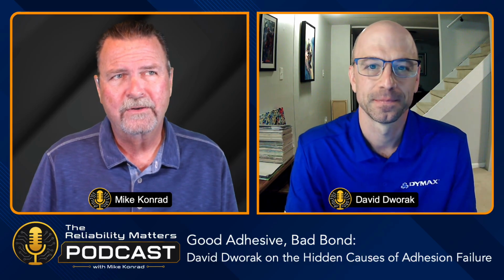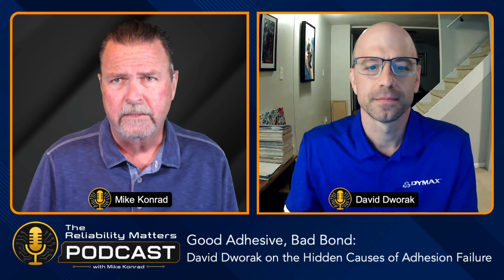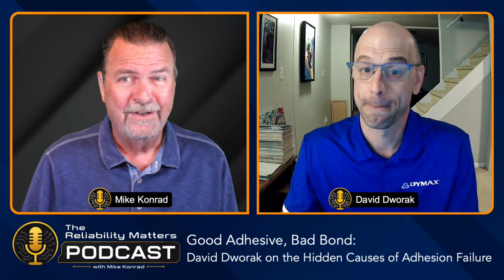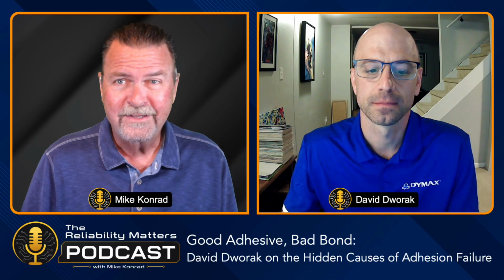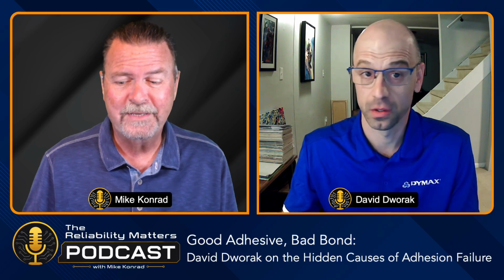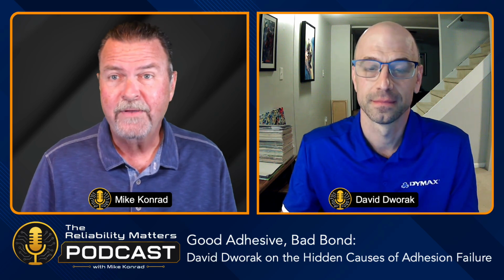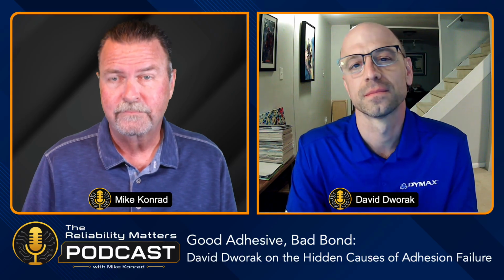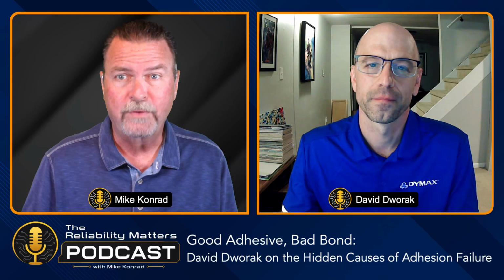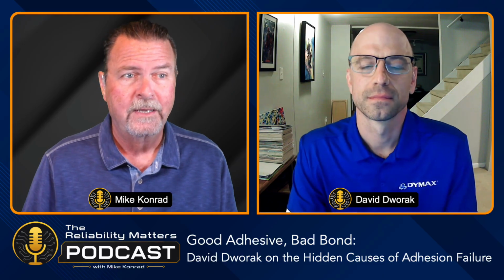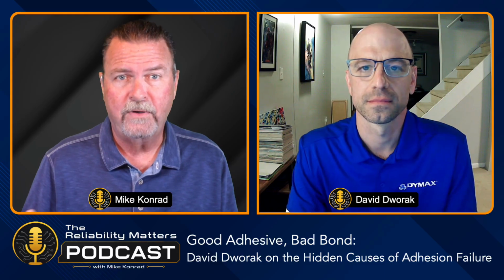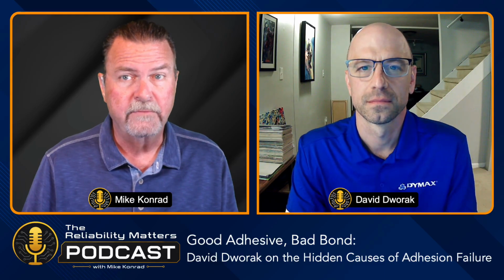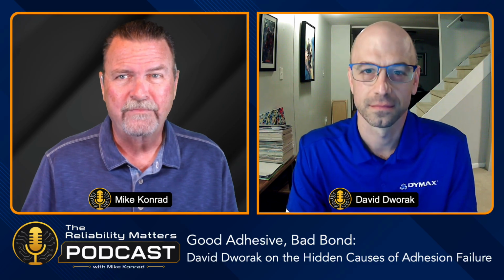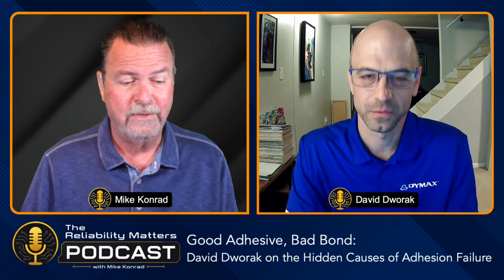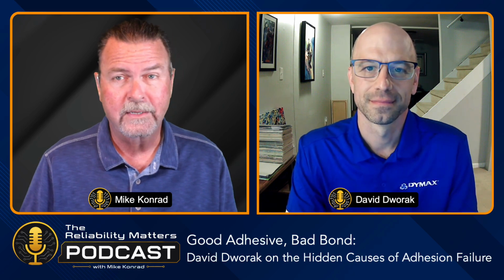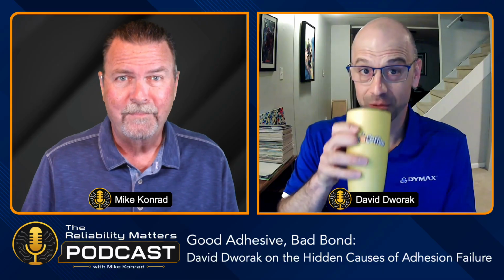Yeah, and I think a good follow-on to that would be, when we say clean, what do we mean? Optically clean, visually clean, or ionically clean? Those are two different things, because no-clean flux, one of its claims to fame is that it leaves no visible residue. And when it's reflowed properly and all the peak reflow temperatures are hit for the right amount of time, and the bad actors or activators and all that are volatilized thoroughly, it generally leaves no visual residue. It does not leave no residue. It leaves no visual residue. So you look even under 32x, you're looking down into the scope and it looks great. You would eat a meal off it. Right. But does that mean it's clean?